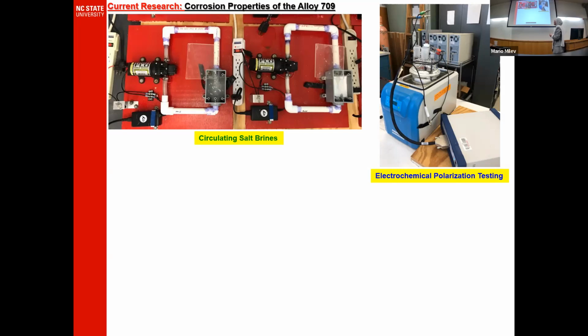This test measures the flow of electrons that results from reduction and oxidation reactions due to corrosion. We apply external voltage or current to disturb the equilibrium state and cause a non-equilibrium state, which is polarization. That allows us to get the corrosion rate in a shorter time scale.